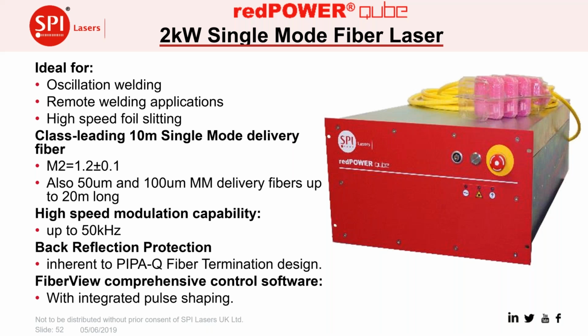Just to highlight back, the laser that we were using for the majority of this work was a 2 kilowatt single mode laser, 2 kilowatts in a 19-inch rack mounted unit. This one had up to a 10-meter delivery fiber, single mode delivery fiber, a beam quality very close to the diffraction limited. But we can also use this with multimode delivery fibers as well if needed. And we get really high speed modulation capability from the laser. So although generally for the oscillation welding we have been using a CW output, if the laser is needed to modulate it anyway in synchronization with the oscillation pattern, then it is possible to do that with these lasers.